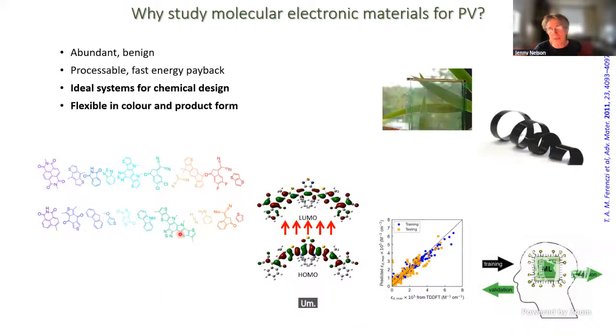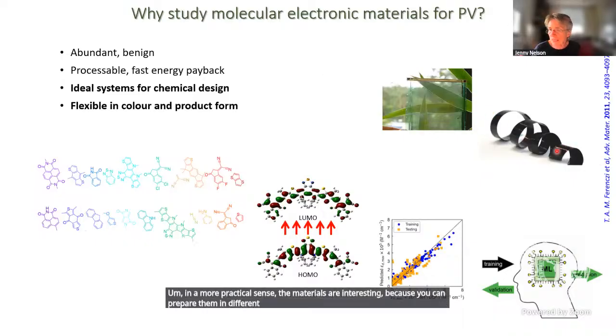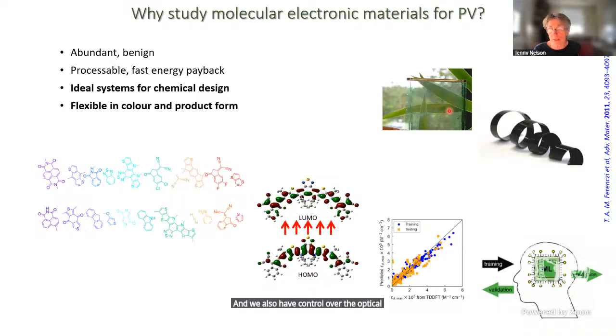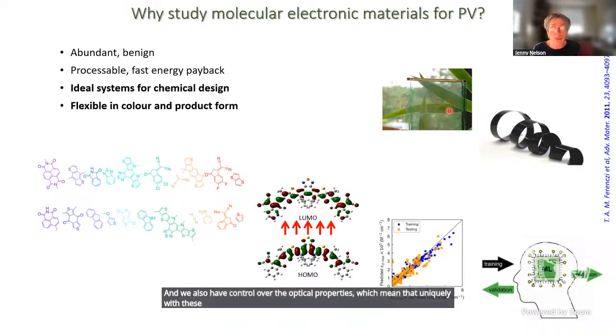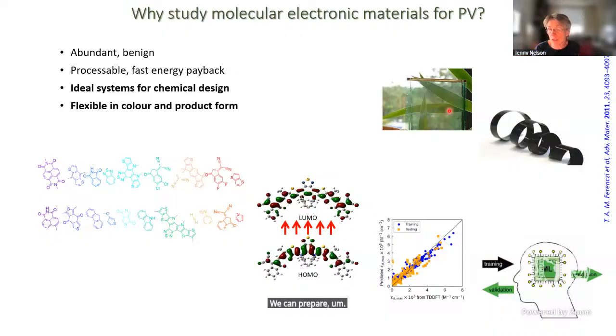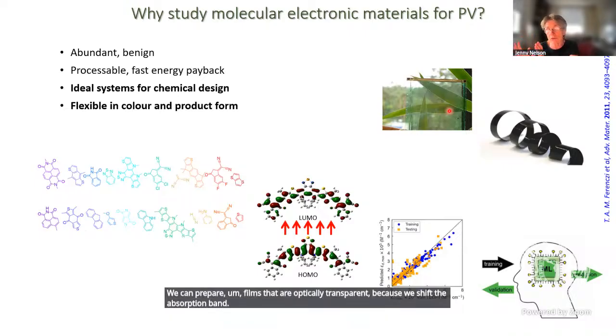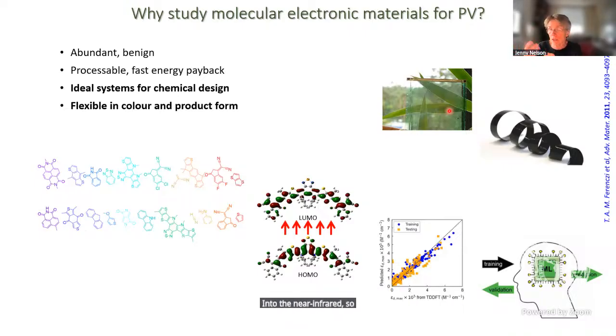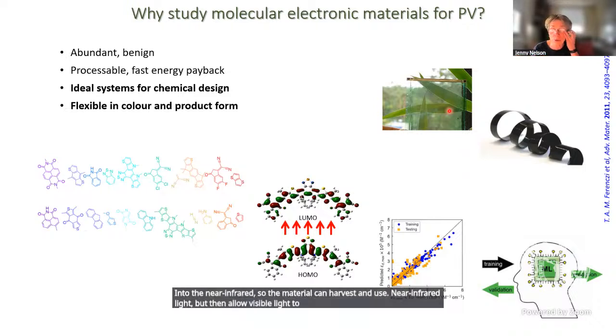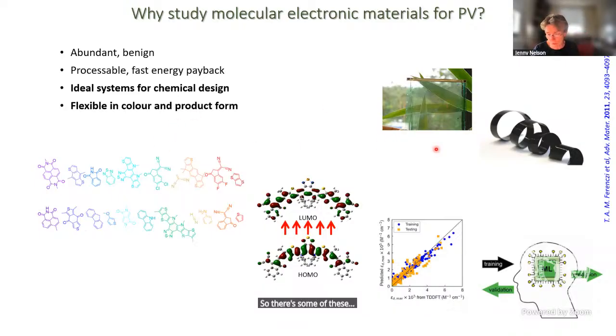In a more practical sense, the materials are interesting because you can prepare them in different formats. You can make relatively conformal shapes. You can make flexible structures. And we also have control over the optical properties, which means that uniquely with these materials, we can prepare films that are optically transparent, because we shift the absorption band into the near infrared, so the material can harvest and use near infrared light, but then allow visible light to pass, and then you could use them in windows, for example. So there's some of these different properties.